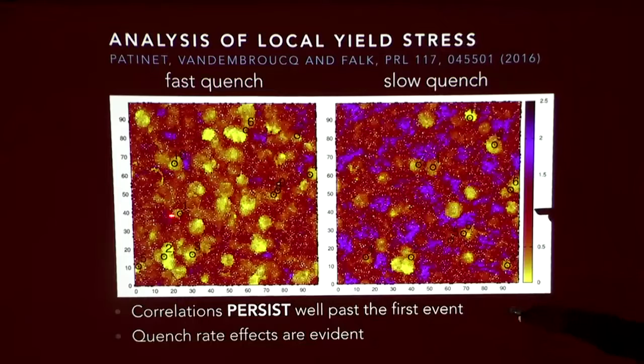The circles here represent, when we shear the system continuously, where the first, second, third, fourth, fifth, sixth, seventh, etc. event occurs as we shear the system. Even out to the 10th event, the low local yield stress measured in the as-quenched system correlates well with where we're getting deformation.